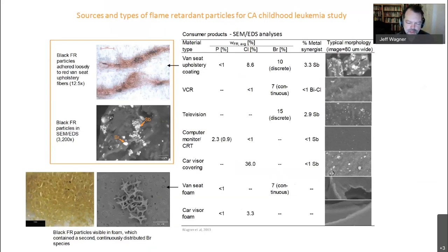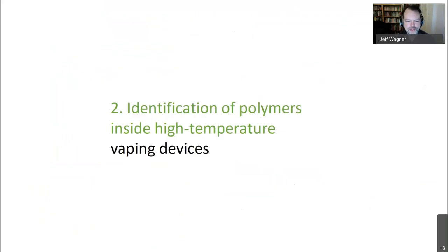In the SEM, its most distinctive property is its gross morphology rather than the flame retardant, but it has this very distinctive foam morphology. You can also see in the left image the black particles, which were the DecaBDE-based flame retardant. However, the foam was also diffused throughout with another type of brominated compound. Also in this project, we looked at various electronics enclosures that had a slightly different morphology. And with that, I will move on to a different type of consumer product in which we found microplastics.